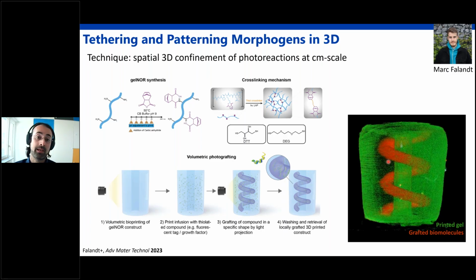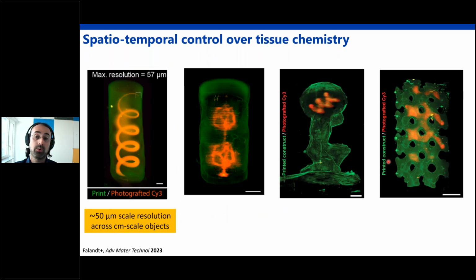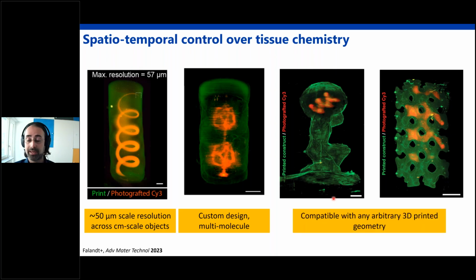So exploiting this phenomenon, we can generate all sorts of arbitrary chemical patterns inside our hydrogel blocks with a resolution of about 50 to 60 micrometers, more or less. And with any arbitrary pattern, as you can see from these convoluted vascular-like networks, also combined with 3D printing. So we can print a complex gyroid and then pattern growth factors in there. In this case, we have a tag with a fluorescent molecule, or also this spiral inside the globe of this Atlas statue. So you can combine multiple molecules as well if necessary, and exploit the powerful technology of bioprinting to make arbitrary geometries with arbitrary patterns of chemical growth factors in them.